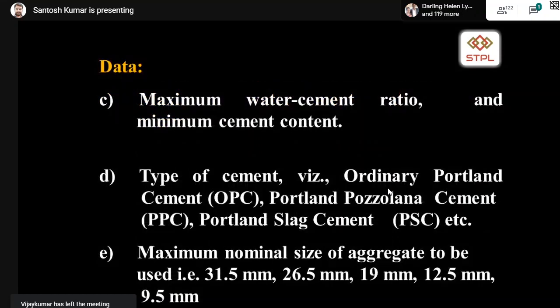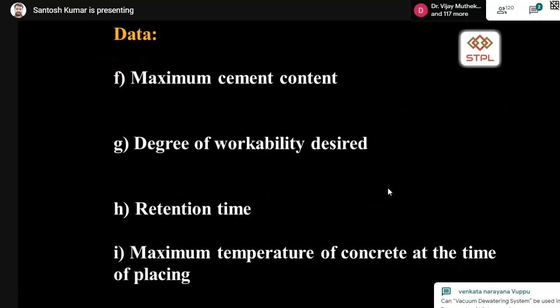And third is, what is the maximum water cement ratio you allow as per the standard, and what is the minimum cement content, and what is the type of cement we are using, OPC, PPC or PSC or composite, whichever cement you can use. These 4 cements are permissible as per IRC 44. And maximum nominal size of the aggregate, 31.5 to 9.5 mm size, you can choose whichever nominal size you want. But one thing I want to add here, when you are dealing with high strength concretes, a lower size of aggregate is most preferable. So maximum cement content, which is 450, degree of workability, retention time, what is the transit time,